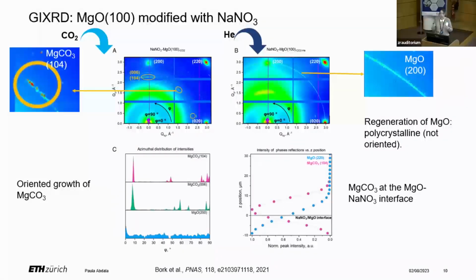So let's look at the diffraction data of the sodium nitrate modified magnesium oxide. We observe indeed the reflection of magnesium carbonate, and what caught our attention is that it's not one single crystal, but something in between a powder and a single crystalline material. So basically, the reflections are at certain angles, especially highly oriented. We can also scan this reflection across the surface of magnesium oxide and locate the magnesium carbonate really growing inward and outward of the magnesium oxide surface. So it's growing at the interface. And if we regenerate this magnesium carbonate to produce again magnesium oxide, what we see is that it's polycrystalline. So there is no orientation of the magnesium oxide with respect to the magnesium carbonate.